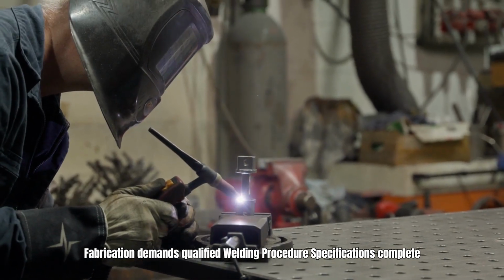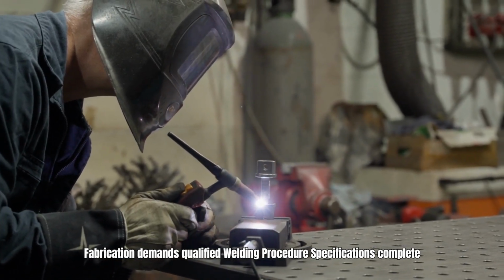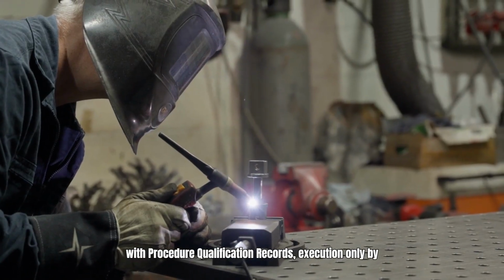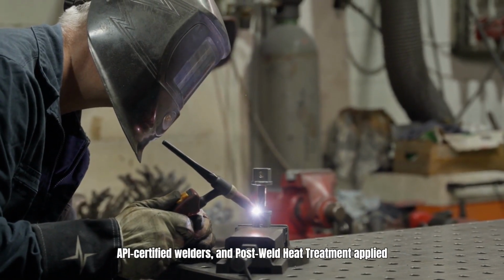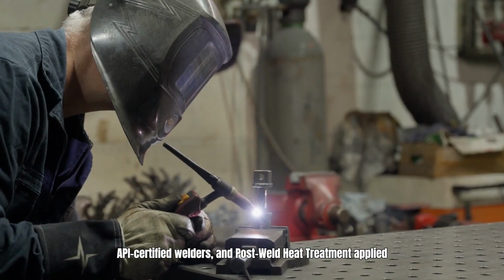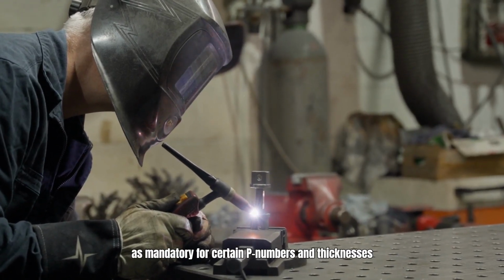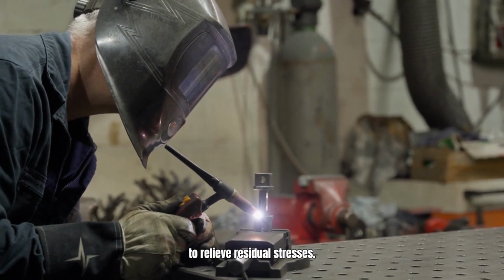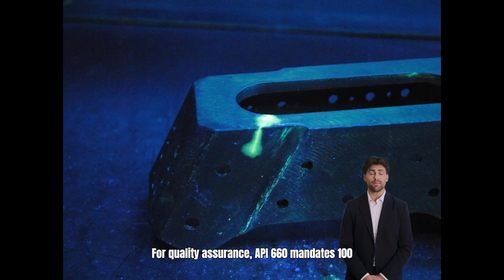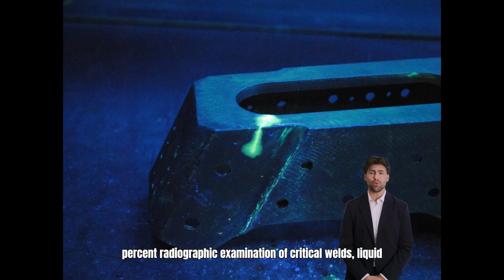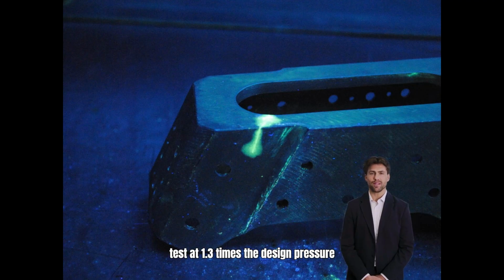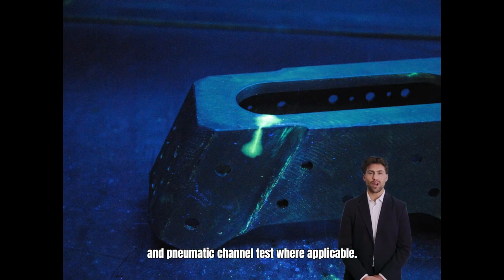Fabrication demands qualified welding procedure specifications complete with procedure qualification records. Execution only by API-certified welders, and post-weld heat treatment applied as mandatory for certain P numbers and thicknesses to relieve residual stresses. For quality assurance, API 660 mandates 100% radiographic examination of critical welds, liquid penetrant testing on full penetration welds and tube-to-tubesheet joints, plus a final hydrostatic shell test at 1.3 times the design pressure and pneumatic channel test where applicable.